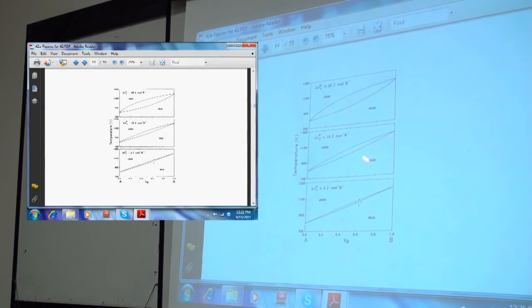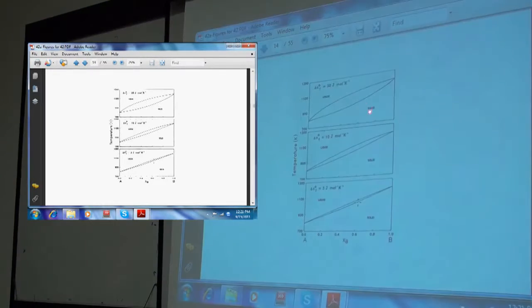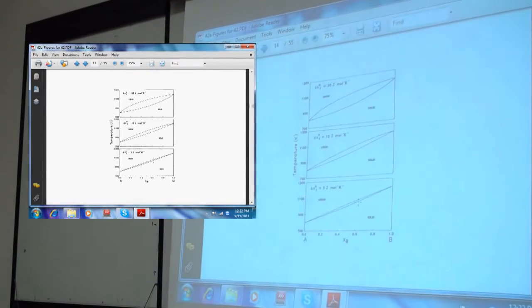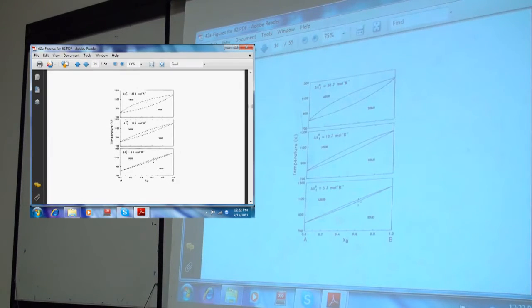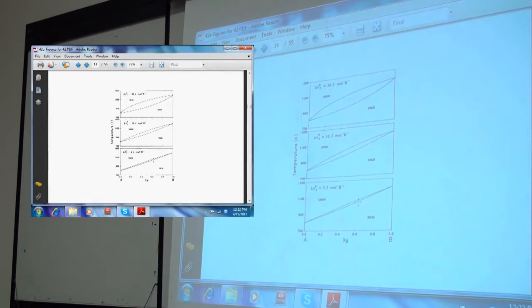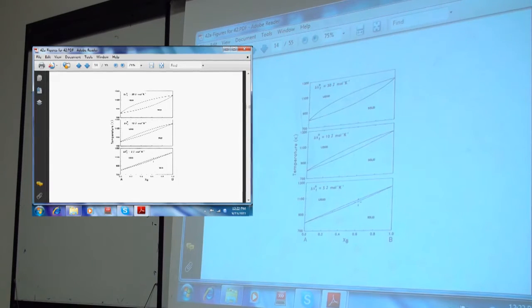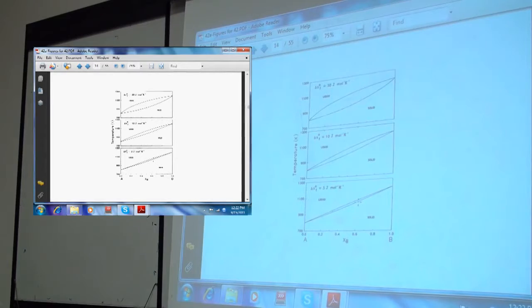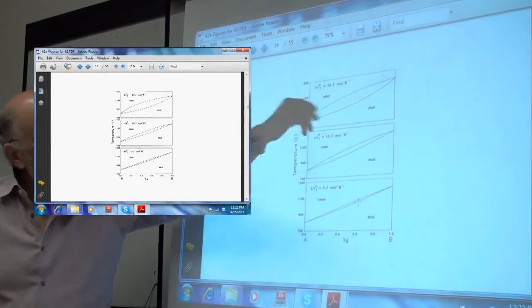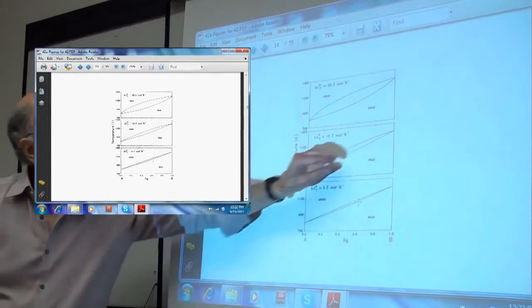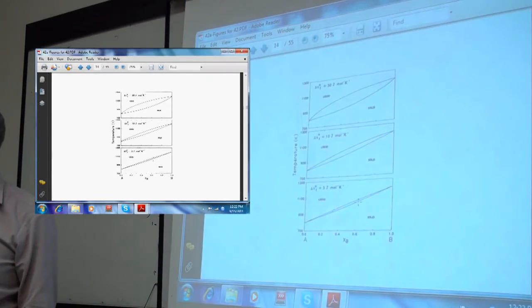Now, here this is solid liquid, but you can say of your phase diagram, rather than solid liquid, this was liquid gas. It's exactly the same thing, but now instead of the Gibbs energy of fusion, you've got the Gibbs energy of vaporization. So just do exactly what we did before on figure 13, but instead of solid and liquid, read liquid and gas. Instead of fusion, read vaporization. But now the entropy of vaporization is about 10 times the entropy of fusion for most materials, because there's a much bigger change in disorder. That's why when you look at a phase diagram between a liquid and a vapor, you see a much fatter two-phase region than you do for a typical solid-liquid region.